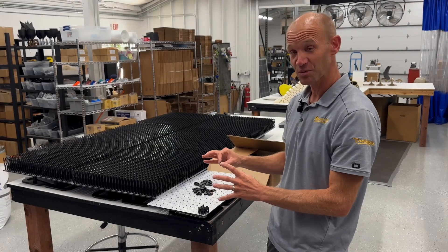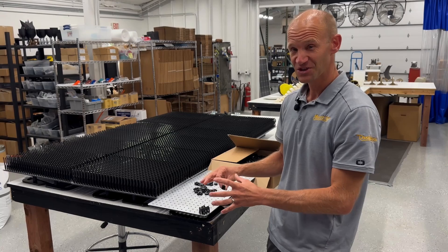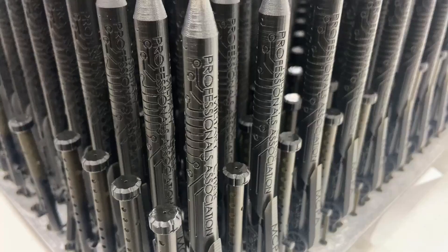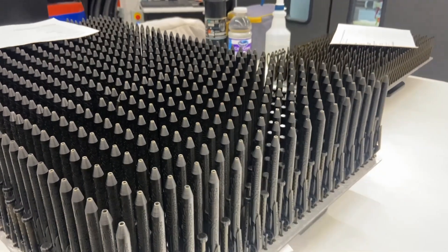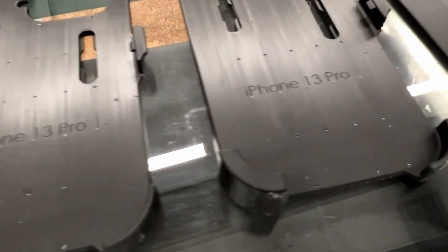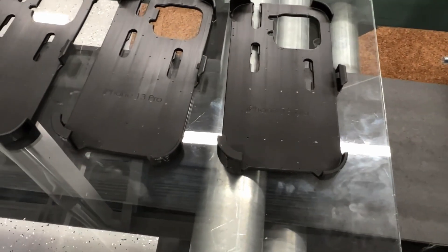The same constraints apply to 3D printing — the more parts you have that are big, the fewer you can fit on a plate. If you're printing a part as big as a grapefruit, you might fit six on a plate. What we've found is that for grapefruit-sized parts and smaller, we can additively manufacture faster than we can injection mold. Anything larger than a baseball or grapefruit size, injection molding is still going to be faster — again depending on mold complexity.